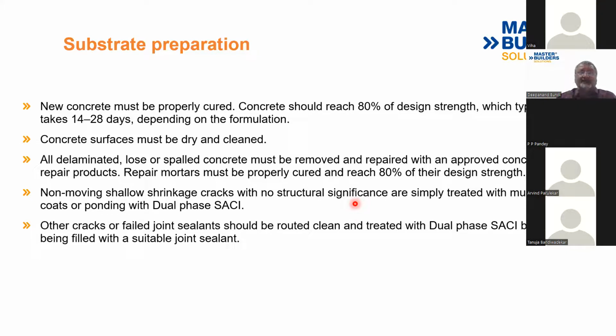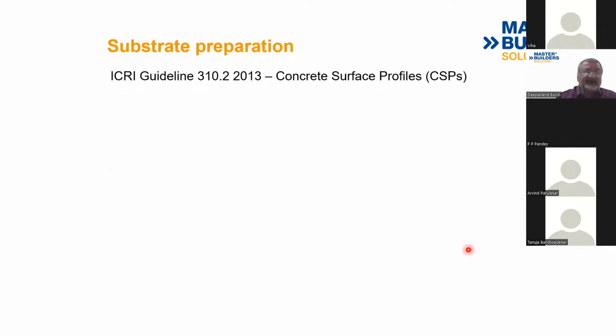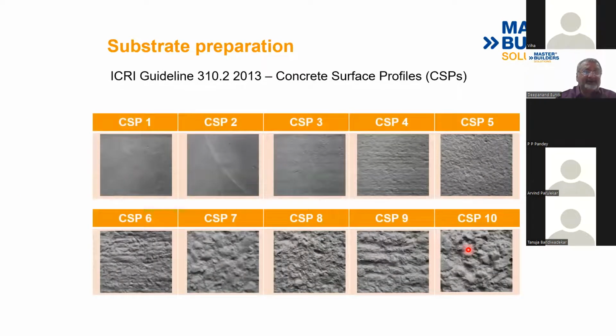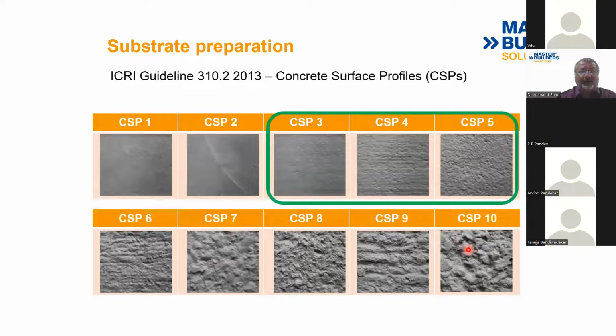There is no adhesion loss or anything per se, but it's only to enhance the performance. Any delaminated or spalled concrete should be repaired, and cracks should be filled up and treated, and only then should you apply this. That's basic substrate preparation that should be done. Generally, the concrete surface profiles, CSP, as per the ICRI guidelines, are CSP 3 to 5. It's much better to have them.